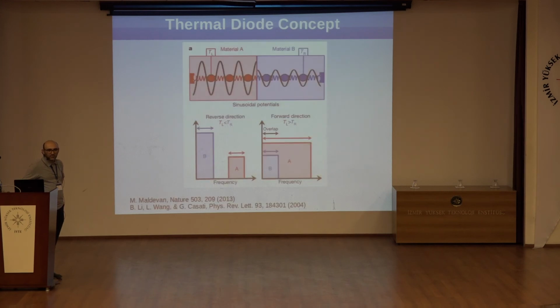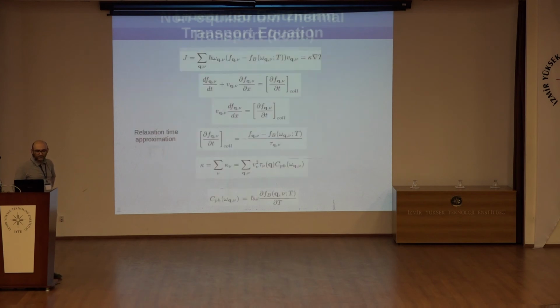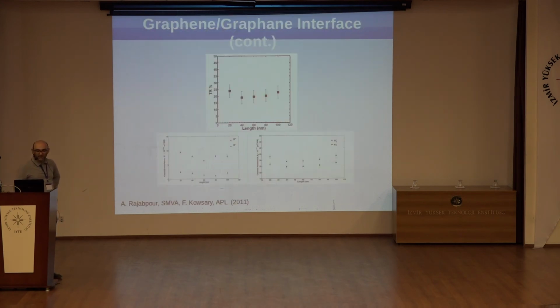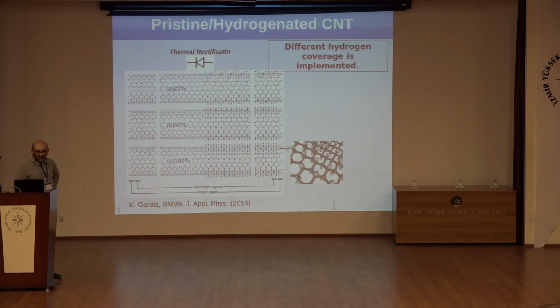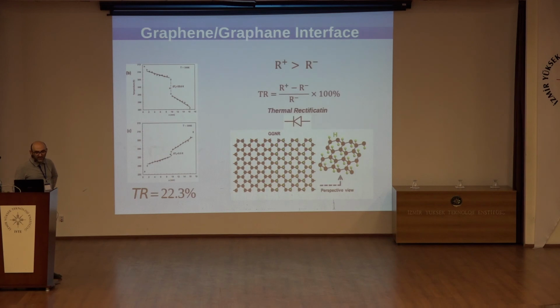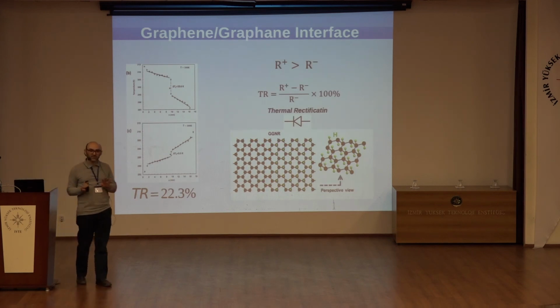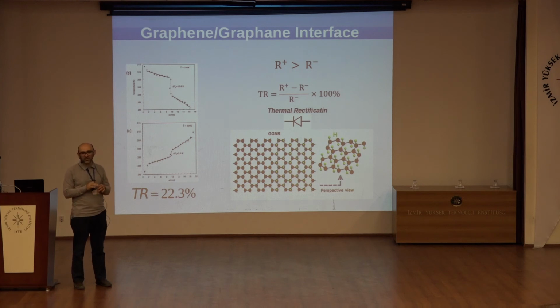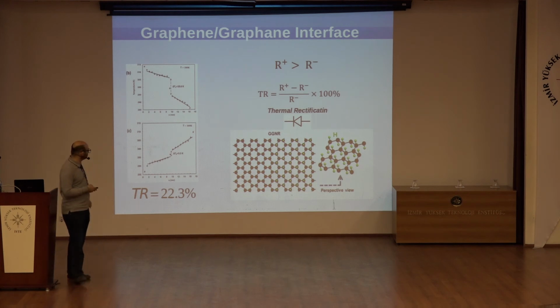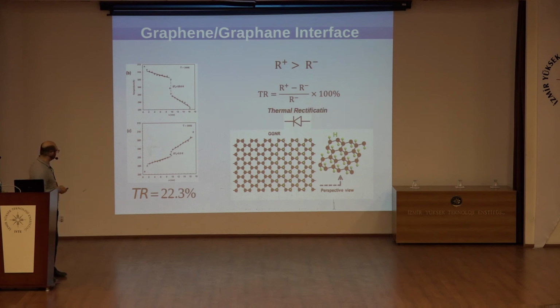But in your analysis of your molecular dynamics data, you mentioned... For the case of, for instance, hydrogenated graphene, we didn't see such a very big mismatch when we reverse the direction of thermal conductivity. For the carbon nanotube case, there was. So, for example, in this picture, there's quite a difference, a factor of almost 3 between the delta T's. Do you just ascribe that to the difference in the density of states when you heat up? The overlap changes? Is that the only reason, or is there any other?